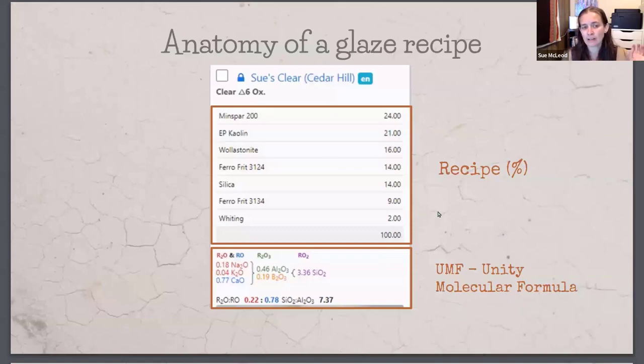And then if you use glazy.org, which is a glaze recipe sharing site, you can search for new recipes. It gives you the chemistry, which is called the UMF, the Unity Molecular Formula. You may have seen this before and wondered what it all means, but this is everything. This is what determines what's going to happen inside the kiln, way more than my material choices in the recipe. So just keeping that in mind, in the UMF, you can see our fluxes are here, R2O and RO fluxes, and then alumina, silica, and boron are glass formers.